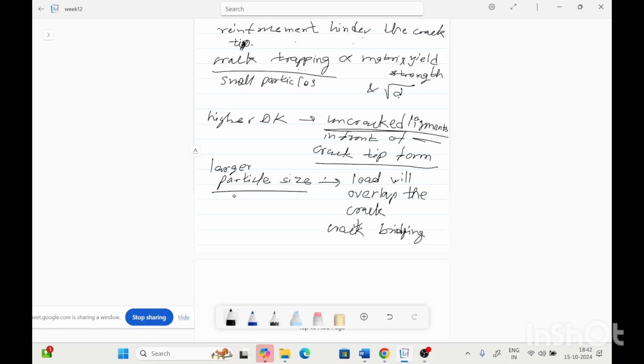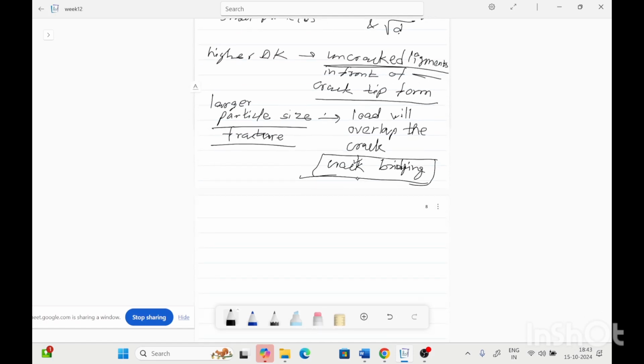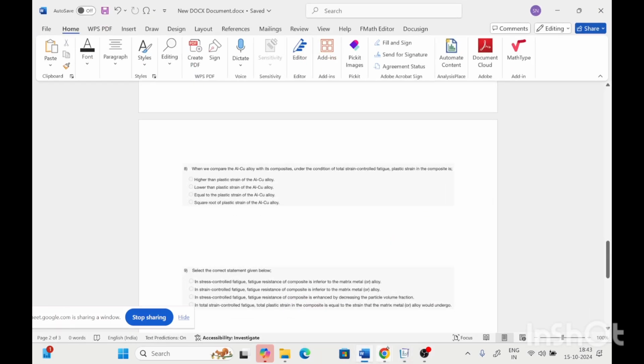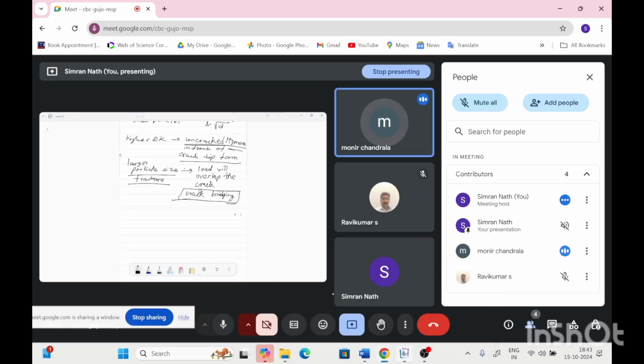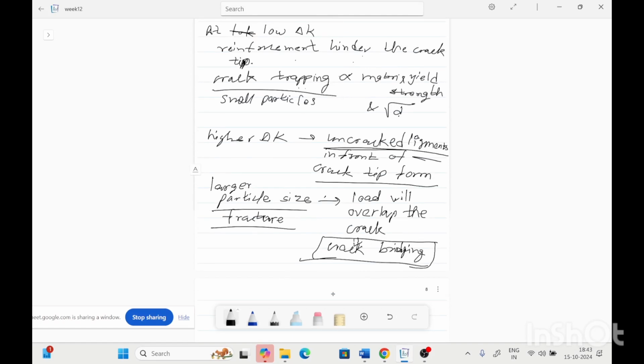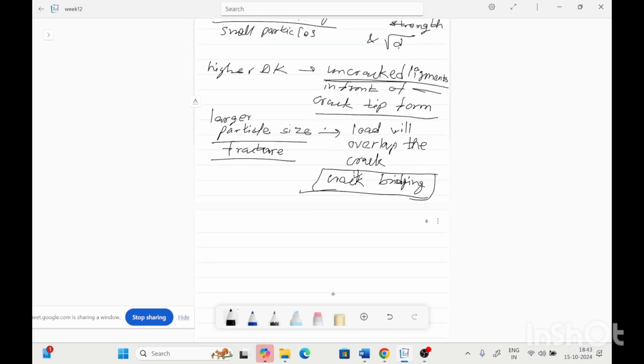Means as the larger particle fractures, because of the fracture of the larger particles, the load will be directly on the crack. Due to the overlapping of load on the crack, it will bridge and close. So that will reduce the crack growth rate. So Monir, did you understand the bridging method? Yes, madam. Means for the smaller particles the crack trapping will happen, and for the larger particles, when they fracture, the load will impact the crack and close it, leading to crack bridging.